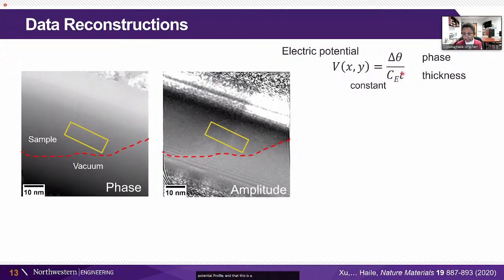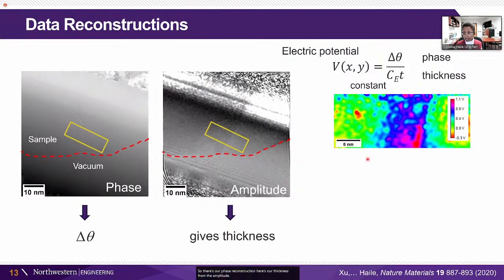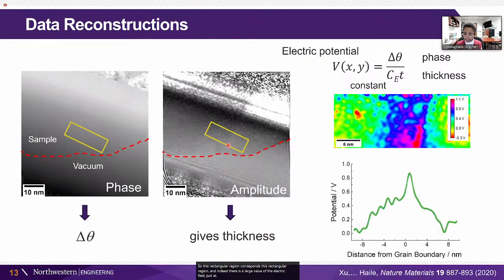And this is a microscope instrument constant, which is known. So there's our phase reconstruction. Here's our thickness from the amplitude. And here is our reconstructed electric potential profile. And what you can see is that this rectangular region corresponds to this rectangular region. And indeed, there is a large value of the electric field just at that interface. And so we integrate that across this, let's call that the Y direction, and we get a profile that looks like here. And we can see that there is a potential right at that interface, which is close to 1 volt, which is really quite a large potential at the grain boundary.